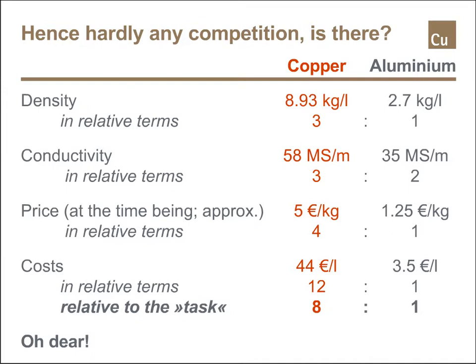against aluminium. And to see this in relative terms, the same quantity that you need for a certain purpose, then you end up with a ratio of 8:1. Actually, you cannot compare the same mass or weight to compare the quantities of the metals, but you must compare the volumes, because the cross-section is decisive. And on top of the cross-section, you have to compare the conductivity. Conductivity is only 2/3 for aluminium, so you have to multiply the cross-section by 3 divided by 2, and then you arrive at a factor of 8 for the price that you have to pay for an equivalent conductor.